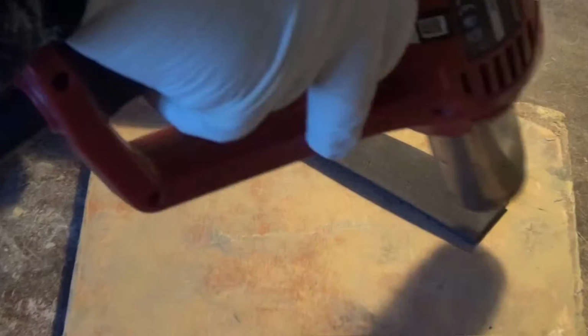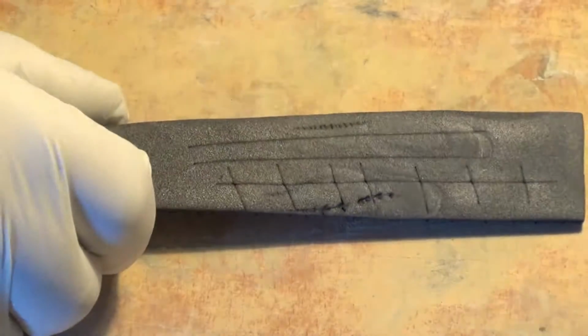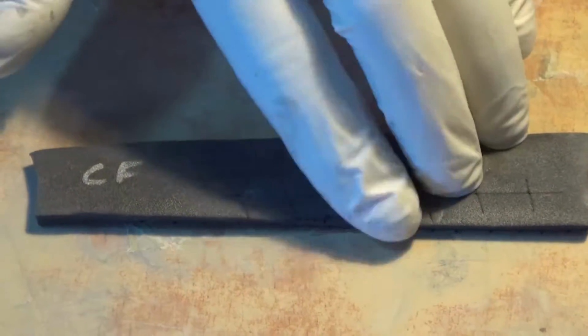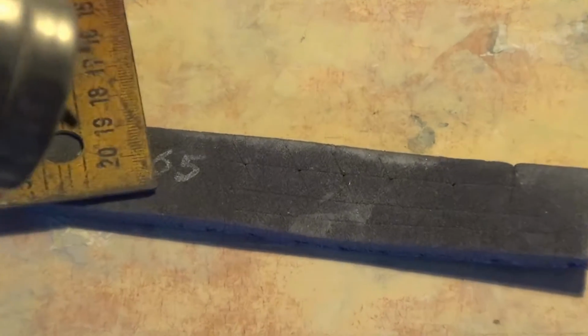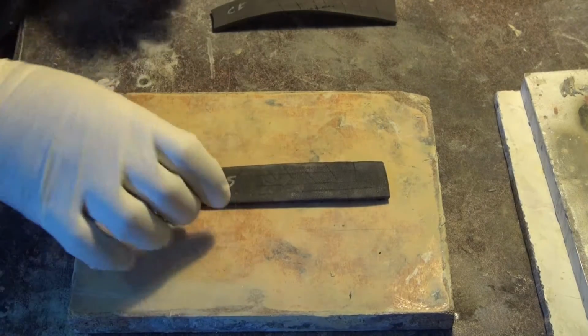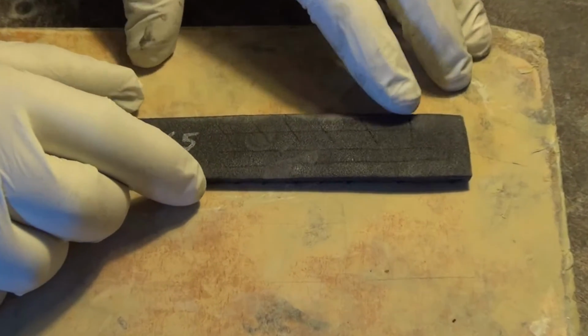The half cuts were then heated using a hot air gun. The craft foam deforms easily when heat is applied. However, heating it did not open the cuts as it happens with EVA foam. When the hot air gun is used to heat the half cuts on the CF65 sample, there are no noticeable changes. This sample does not deform with heat as much as craft foam. The half cuts are still visible, but they did not open.